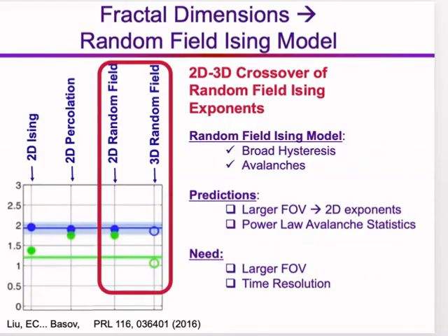Now, as I said as well, there are other exponents we can extract. This graph here focuses on comparing that data to the theoretical models I listed, just focusing on those fractal dimensions because they were the most discriminatory. I mentioned as well counting how many clusters of a particular size. It turns out that all the theories predict the same number on it, and the experiment's pretty close to that, so it wasn't that informative. But these are the informative exponents here.